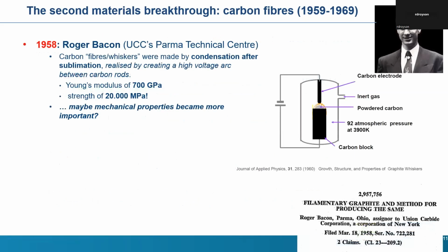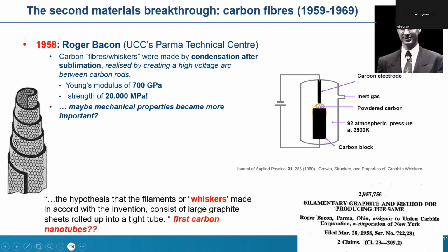And the first person who really looked for fiber-like materials was Roger Bacon, again in the Union Carbide Company Research Center, Parma Technical Center of Union Carbide. And he, in fact, produced by first sublimating carbon and then condensating it. Sublimation was realized by a high voltage arc between carbon rods. And then the sublimated carbon was condensated and formed a kind of fiber-like, on a nano level, fiber-like material. And without going in detail, it's very exciting to read how they made a guess, in fact, of the Young's modulus, but he was reaching a Young's modulus of 700 gigapascal and an estimated tensile strength of 20,000 megapascal.